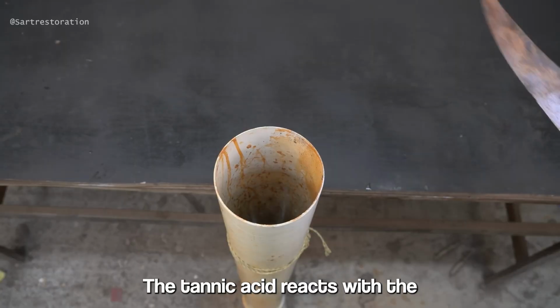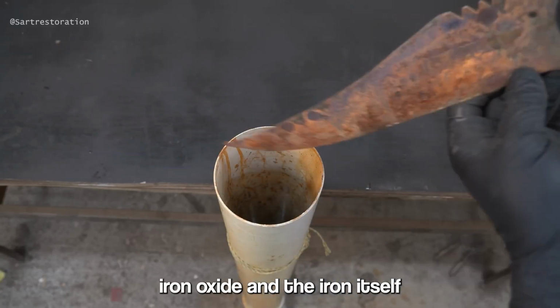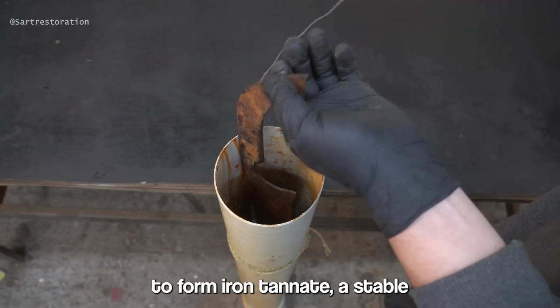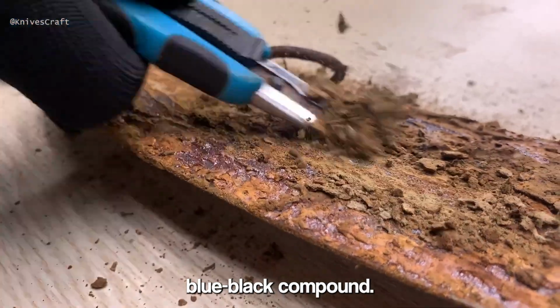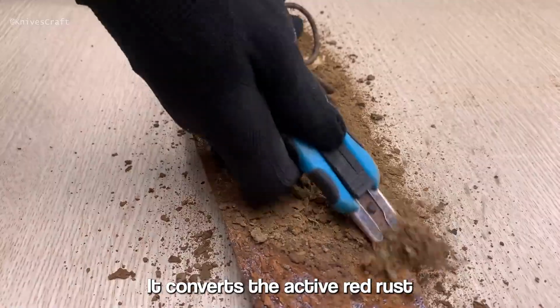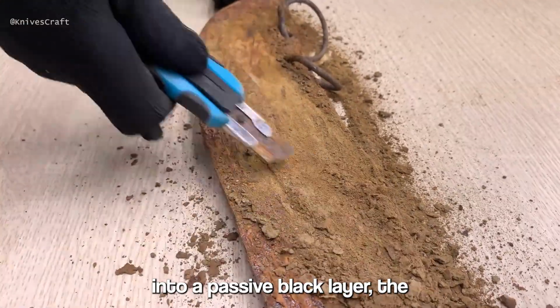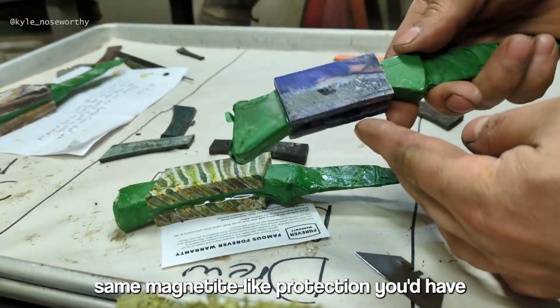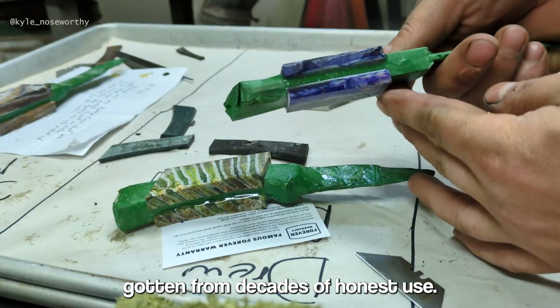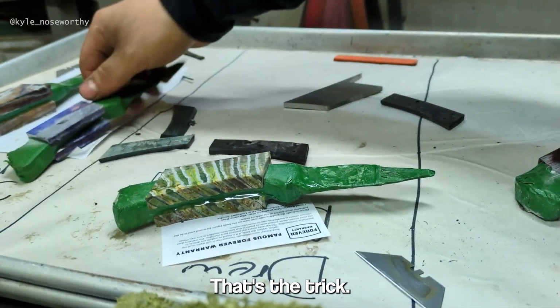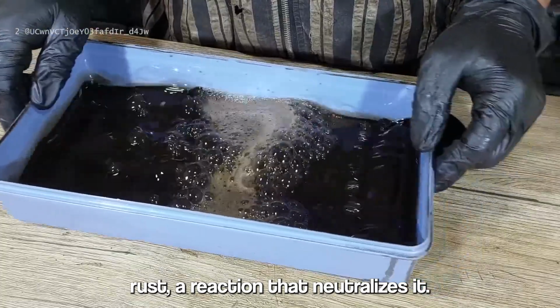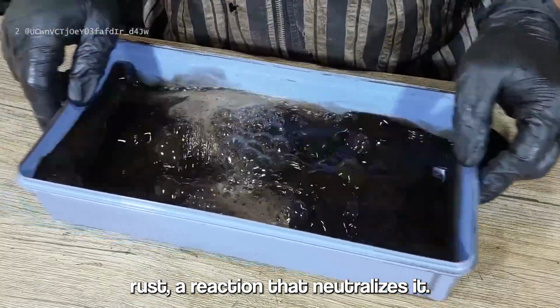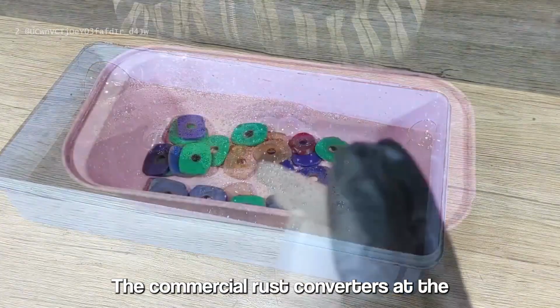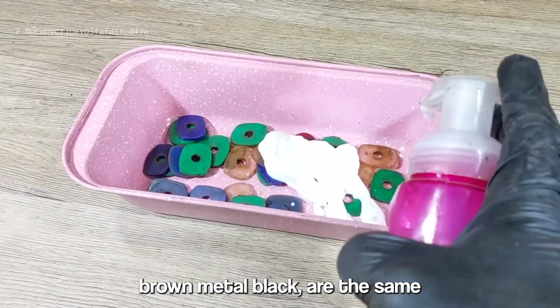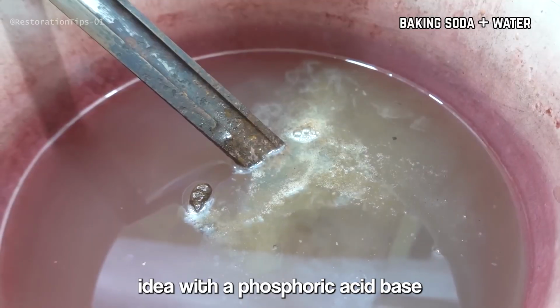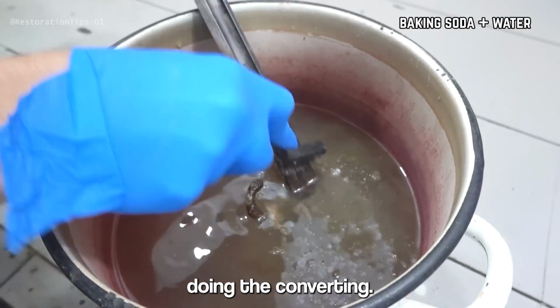The tannic acid reacts with the iron oxide and the iron itself to form iron tannate, a stable blue-black compound. It converts the active red rust into a passive black layer, the same magnetite-like protection you'd have gotten from decades of honest use. That's the trick. Not a coating that hides the rust, a reaction that neutralizes it. The commercial rust converters at the hardware store, the ones that turn brown metal black, are the same idea with a phosphoric acid base doing the converting.